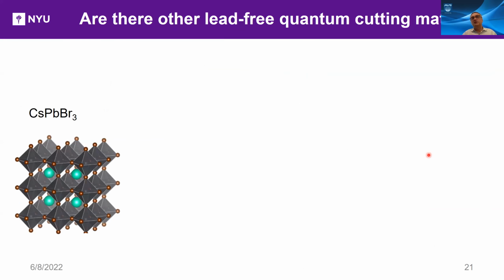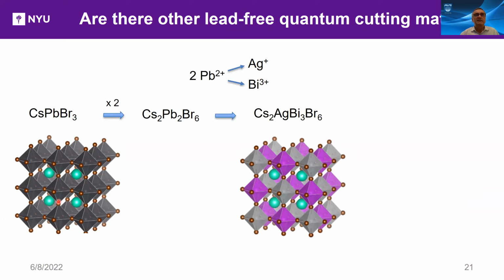Okay, so let me first answer the question of, are there other lead-free quantum cutting materials? If one thinks about cesium lead bromide, with the bromide atoms on the corner, lead in the center, and cesium in the center of the cube. And if I double that unit cell, here I show actually 4 of them. And then think of taking 2 of the lead, that's 4+, and then hetero substitute with silver, which is a monovalent, and a bismuth trivalent ion. So every other octahedra is going to have either a silver or a bismuth, so that we have the charges compensated. This color scheme of purple, gray, take your pick, is meant to depict the alternating silver and bismuth.